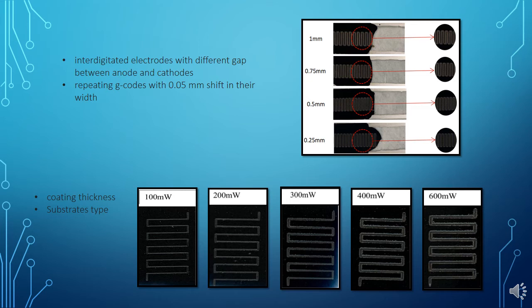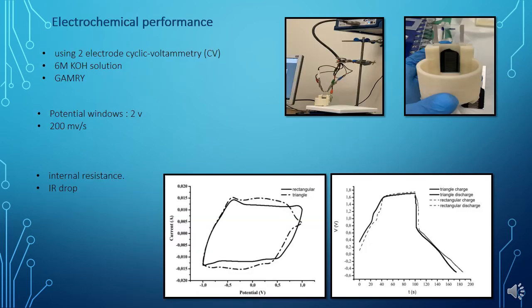It can be noticed from the image that at low power, the finger lines are not entirely ablated and electrically isolated electrodes cannot be constructed. However, at higher power levels, more than 300 milliwatt, finger lines were completely ablated and electrically isolated from each other. On the other hand, at higher laser powers, the width of finger lines increased because of the increased spot size of the laser beam during the laser ablation process and the lateral heat transportation.